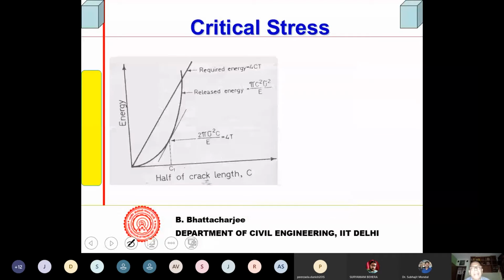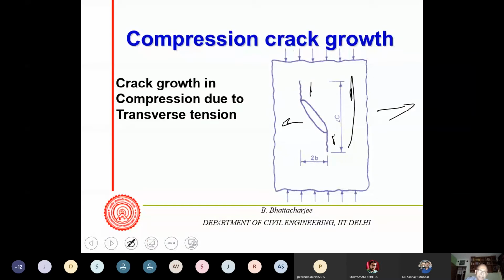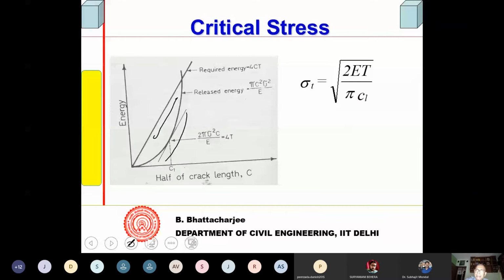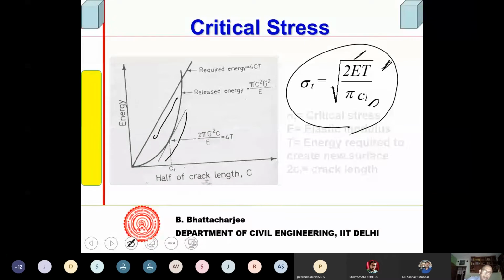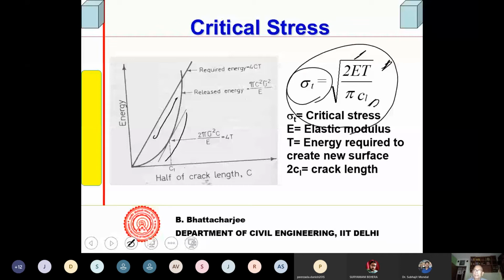And theoretically one can derive this critical stress. Surface energy, strain energy release, which is a function of an elliptic hole that I mentioned earlier. This is 2c, an already existing crack. So it's a function of 2c, and it has been found in terms of the half pore or pore radius, or half crack width, crack length. T is the surface energy, E is the elastic modulus. This is called the critical tensile stress: elastic modulus, energy required to create new surface, and 2c is the crack length. That's what existed. Now in concrete or cement paste, you'll have too many of them.